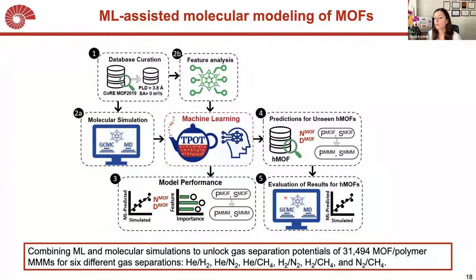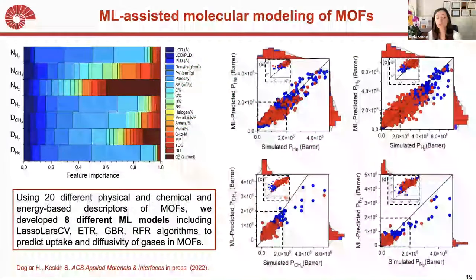So we were able to make a large amount of prediction for a lot of permeability data for a lot of materials. In order to do machine learning, you need to choose some descriptors. And we tried our best to choose the simplest descriptors. When I say simplest, the descriptors that you can calculate very quickly or measure experimentally very quickly, like percentage of the metal atoms or porosity of your material.